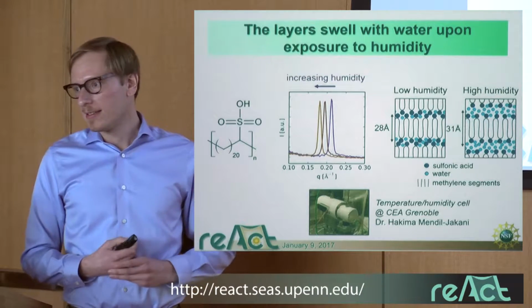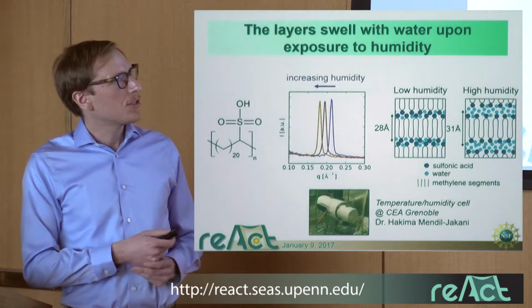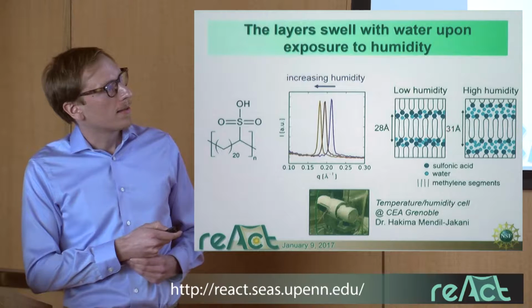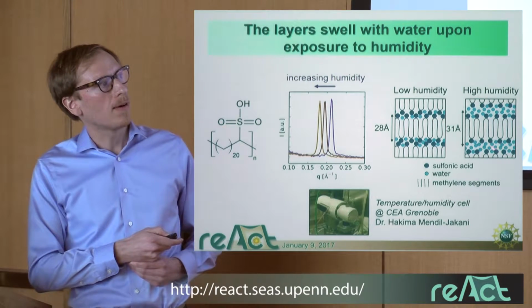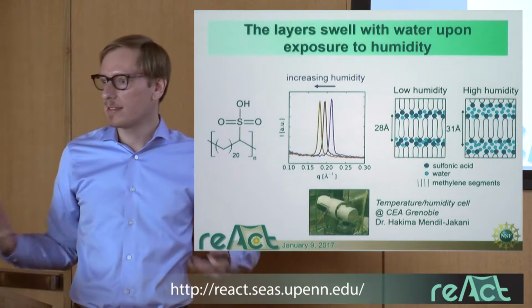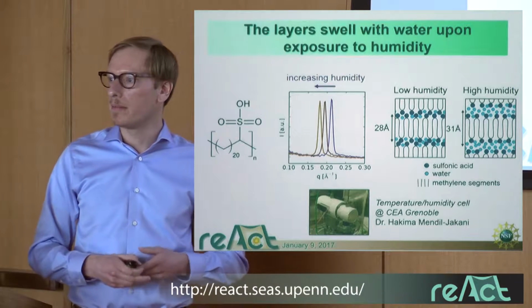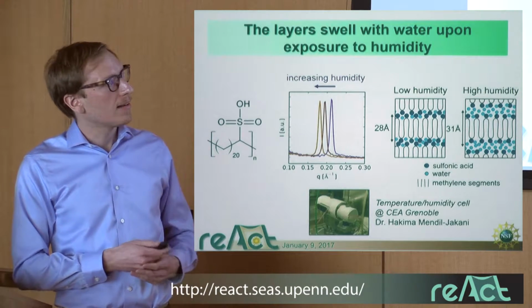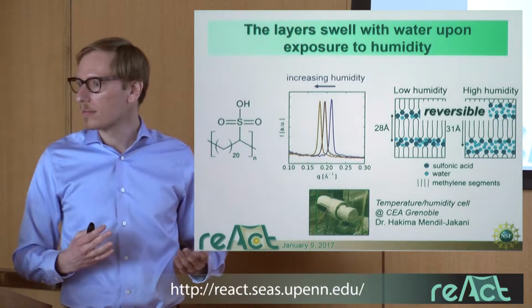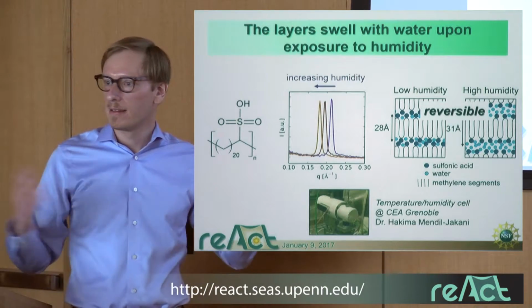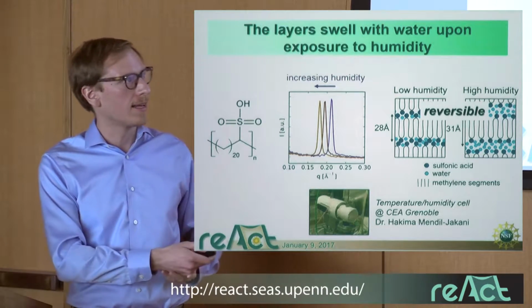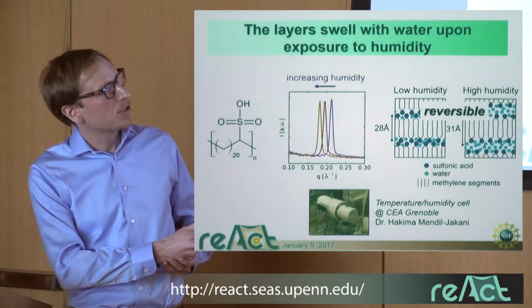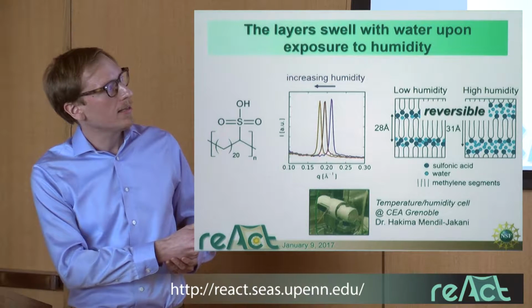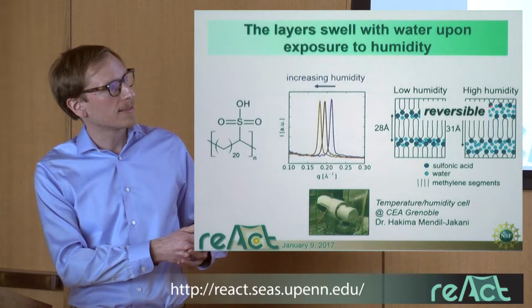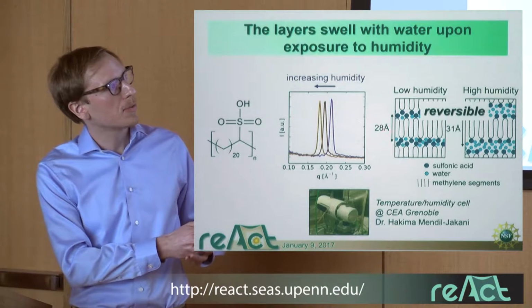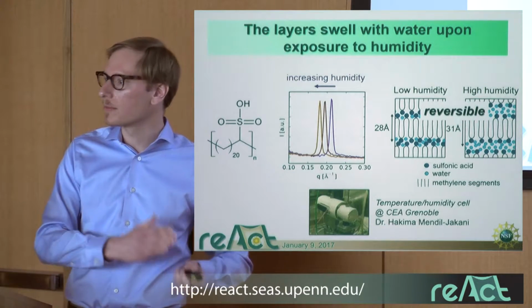Experiments at Grenoble that I did this past summer showed that these layers can be swelled with water simply by increasing the humidity of the environment around the membrane. And this is actually reversible. So if we remove the humidity, the water leaves the membrane, leaves these layers, and this shifting of the X-ray scattering peak here shows the changing of the layer spacing here. So we're going from 28 to about 31 angstroms.